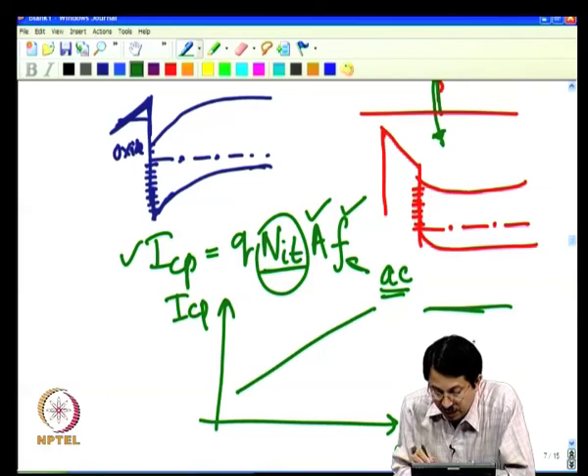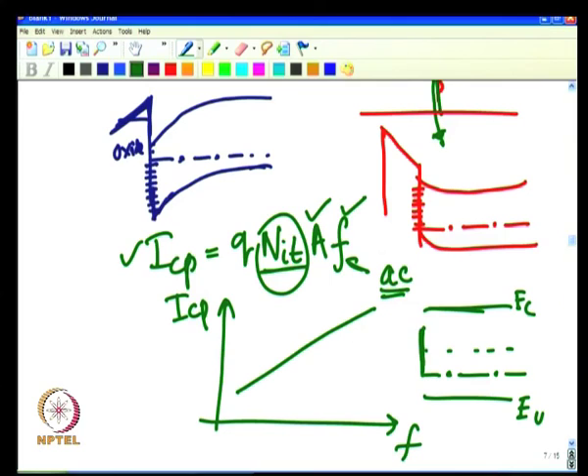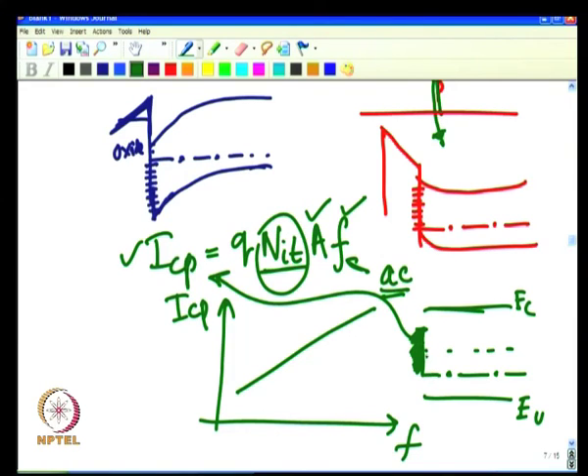The charge pumping measurement integrates traps across the band gap from flat band to inversion — spanning from below mid-gap (Fermi level at flat band) to above mid-gap (Fermi level at inversion, ~2φB). Variants of charge pumping can even give the energy distribution of traps in the band gap. This technique is more sensitive than capacitance measurement methods and is highly accurate for measuring interface trap density in transistors.